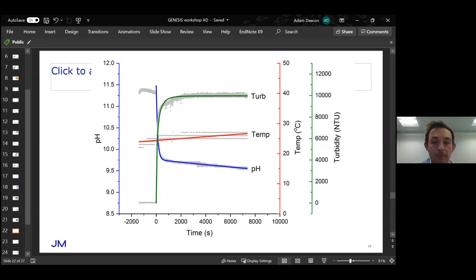The most interesting thing for us is the turbidity measurements. We see the turbidity increases very rapidly before it plateaus out. What we can assume from this plateau is that no more solid is being produced once the turbidity is plateaued. We can actually reduce the reaction time of our materials significantly by monitoring in this way.